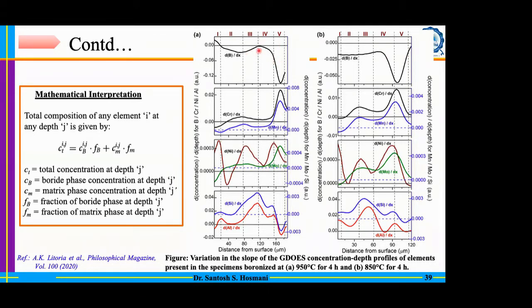What is the zero slope? Zero slope means that there is a stagnation of that boride column. It is unable to grow further. And why is that stagnation there? That is because of the accumulation. If you compare the boundary line between zone 3 and zone 5 with respect to the aluminum and silicon, you realize that something is associated with the aluminum and silicon segregation in the matrix. And that also we confirmed in this particular analysis.